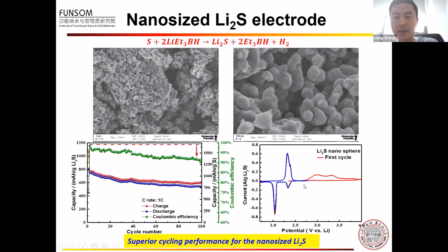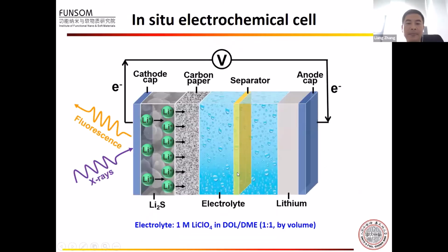The right figure shows the CV results for the lithium sulfide material, and the curves are very similar to that of the commercial lithium sulfide. These results again indicate the different reaction mechanism for the first and the following charge processes. So we designed a very simple electrochemical cell to perform the in-situ operando XAS experiment.